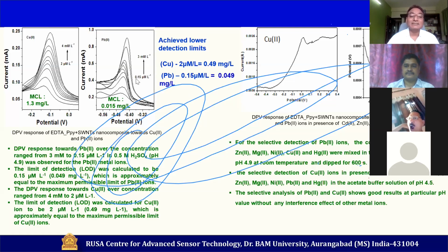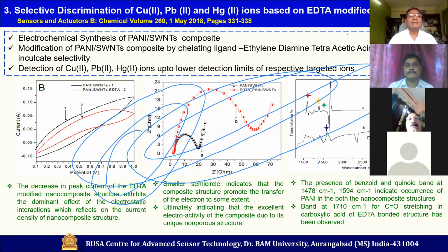But as far as lead is concerned, we could not reach, because MCL for lead is 0.015, but we could reach 0.049 only. So somehow we were not happy with this result. We again did the cross sensitivity study as well, and we got substantial peak only for copper and lead. We could discriminate the metal ions. And then we went ahead and did polyaniline with SWNT. Earlier we did polypyrrole with SWNT. This is polyaniline with SWNT and modified with EDTA again, right?